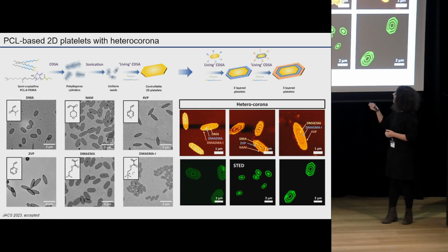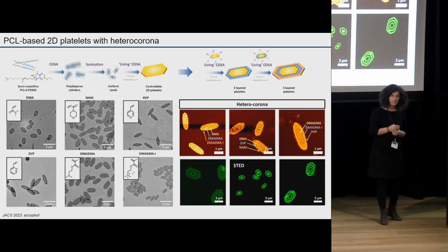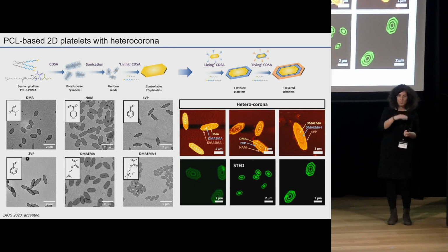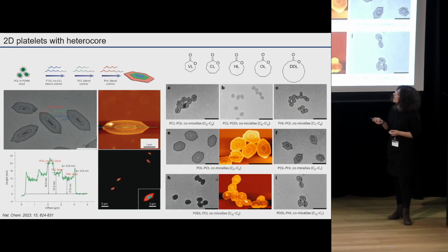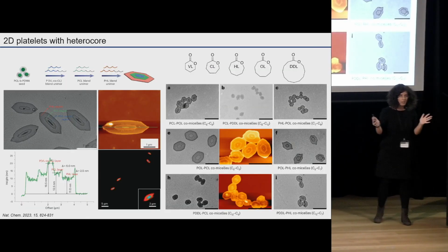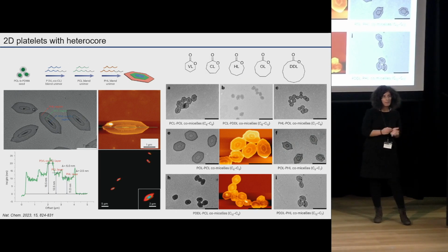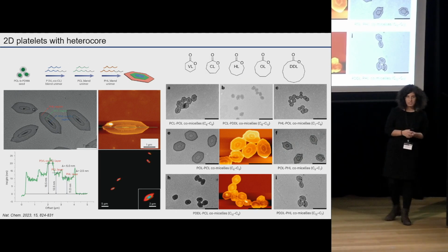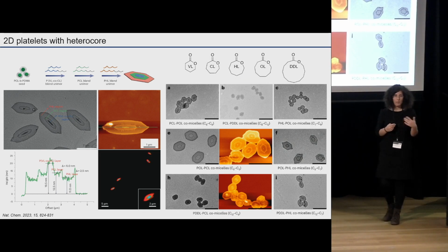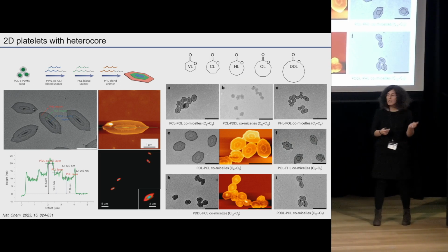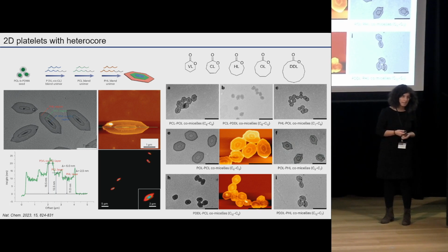And in this case, we're building nanoparticles that have many different layers, and we have many different functionalities. And as you can see here in this picture, for example, with a confocal representative, we labeled only a few layers of our nanoparticle, and we know exactly what that polymer is inside our single structure. We cannot just manipulate the hydrophilic part of a nanoparticle, we can also manipulate the hydrophobic part. So I talked a lot about polycaprolactone and polylactide as a choice of polymer, but we can actually go to any polyester that we want.